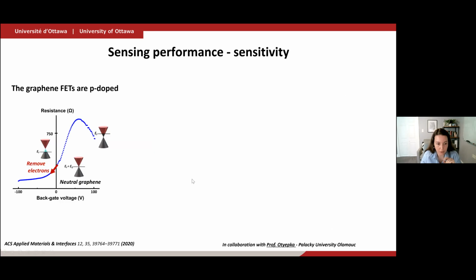And so to give you a sense of what the science is behind it, if you measure the resistance of a graphene field effect transistor as a function of backgate voltage, you'll find essentially this low and then high and then low again. It's an ambipolar field effect where the highest resistance represents the Dirac point in graphene, or the neutrality point. So that's where graphene is least metallic; it gets more metallic away from that Dirac point. It's most resistive close to that Dirac point. And the very simple way to tune this Fermi level through the Dirac point and make graphene p-doped or n-doped is really to apply backgate voltage.